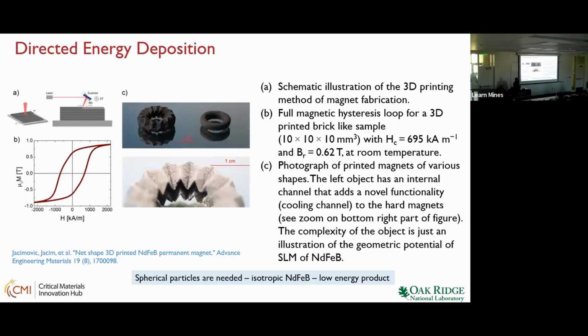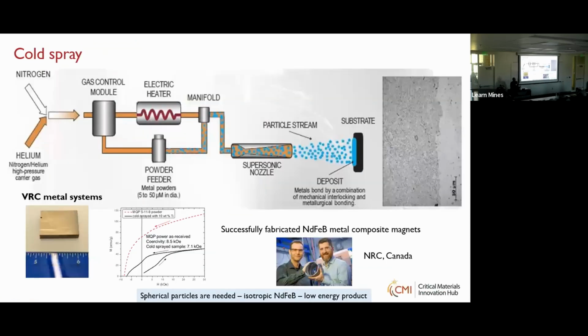And the moment you hit any of the magnet powders with the laser during printing, at the temperature of the 2-14-1 phase, the structure decomposes. It loses the coercivity, it becomes soft. So that's why you cannot heat it to dissolve, it really reacts. So that's where we thought, maybe can we look at a lower temperature.